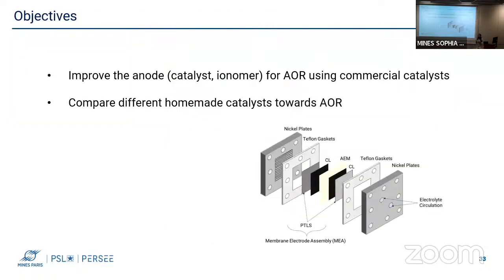Since the ammonia oxidation reaction is the more sluggish and the less studied in the literature, the objective of this part is to improve the anode conditions, specifically in terms of catalyst loadings and ionomer concentrations for the ammonia oxidation reaction. First, using commercial catalysts, and then, in an attempt to improve the performance from the commercial catalyst, we prepare homemade ones.